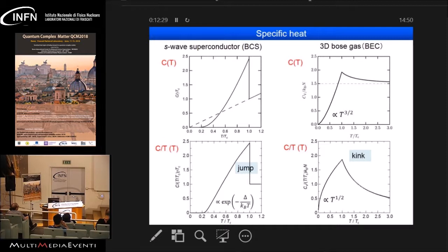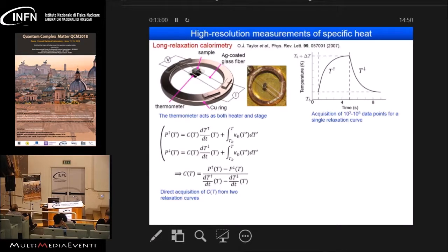That's what you know, right? However, in the case of BEC, what happens is that C over T shows a gradual increase in the normal state towards Tc, and we don't see any jump at Tc. But we have a kink like this. And in the superconducting state below Tc, we have a power law dependence. In this case, C over T is proportional to the square root of T. Okay, so we want to look at this problem.